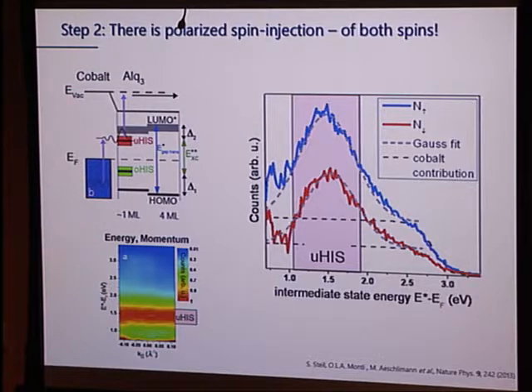And then if we do the photoemission and we measure how many spins up and down we get in this excited state here, this is the one that we want. Remember, we want to inject into it or from it. Then we see that we do get, this is properly normalized, a different extent, similar shape, but different extent of spin up versus spin down. So there's spin polarization. We do see both spins, but there's spin polarization present.